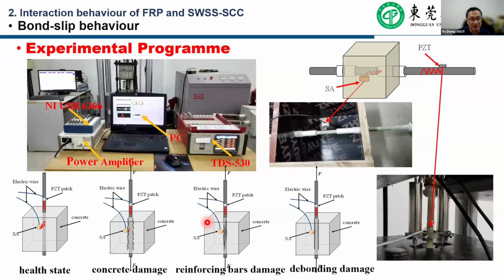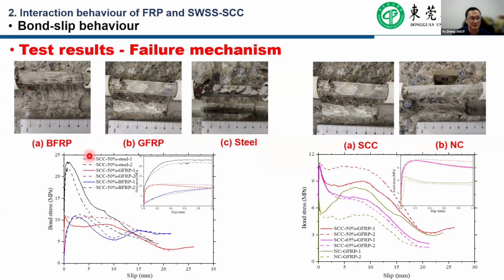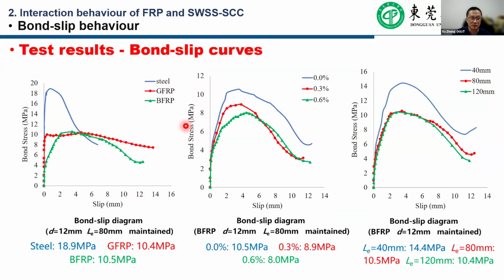bond test. It can be seen in those figures, compared to the steel reinforcement, the bond strength will be lower due to the lower elastic modulus, and the bond stiffness also can be reduced due to use of the FRP reinforcement, and some damage can be found after we remove the concrete. And comparing two concretes, the self-compacting concrete and the normal concrete, due to the better compactness of the self-compacting concrete, we can find the higher bond strength in the FRP reinforced seawater and sea sand self-compacting concrete. And in those behaviors, those results can be expected.